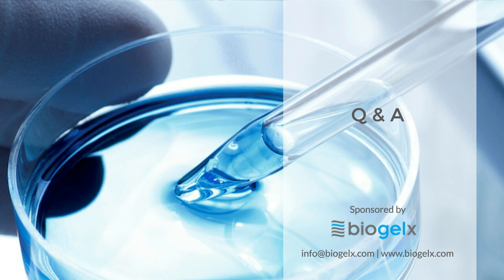So this is Rob Schwartz. Although we didn't include this data here because we tried to include one gold standard in the data that we presented using Matrigel, we have compared them to collagen gels as well as PEG hydrogels. One of the challenges with these different gel systems is that the elastic modulus significantly exceeds the elastic modulus that's found in the liver.